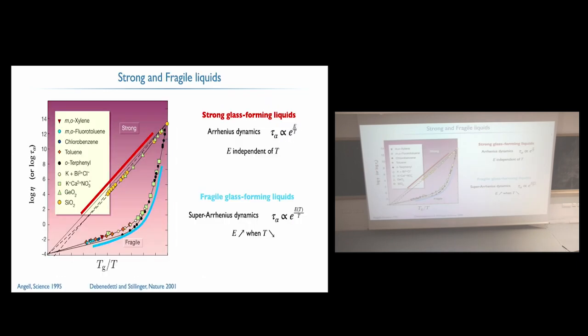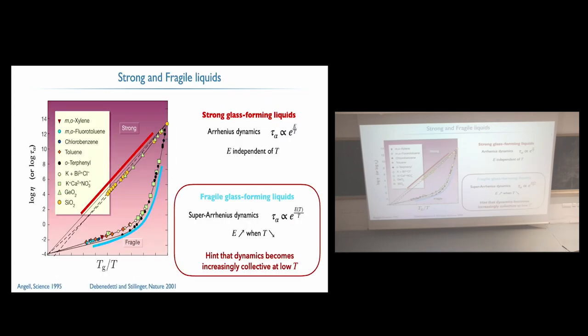In addition to, yes? So this barrier, so SiO2 and also GeO2, I think they're network forming liquids. Compared to all the other molecules which are completely disordered, these have a tetrahedral arrangement that they prefer, and this gives rise to a network. I think we understand well that the energy barrier is related to breaking this network. I'm not 100% sure that all the strong glass forming liquids are network forming, but at least in these cases, this is what happens. And the others don't form preferentially a network, it's just random packing. Yeah, no local order.